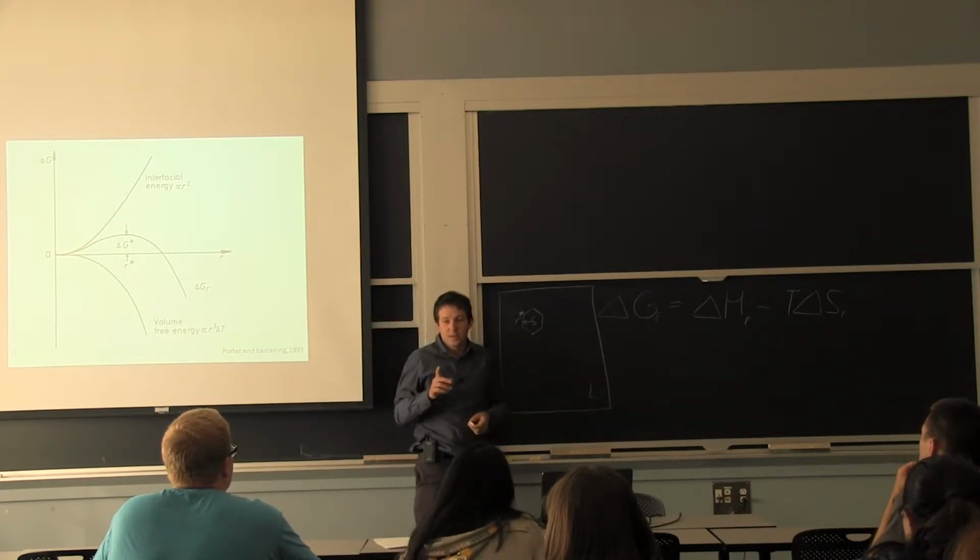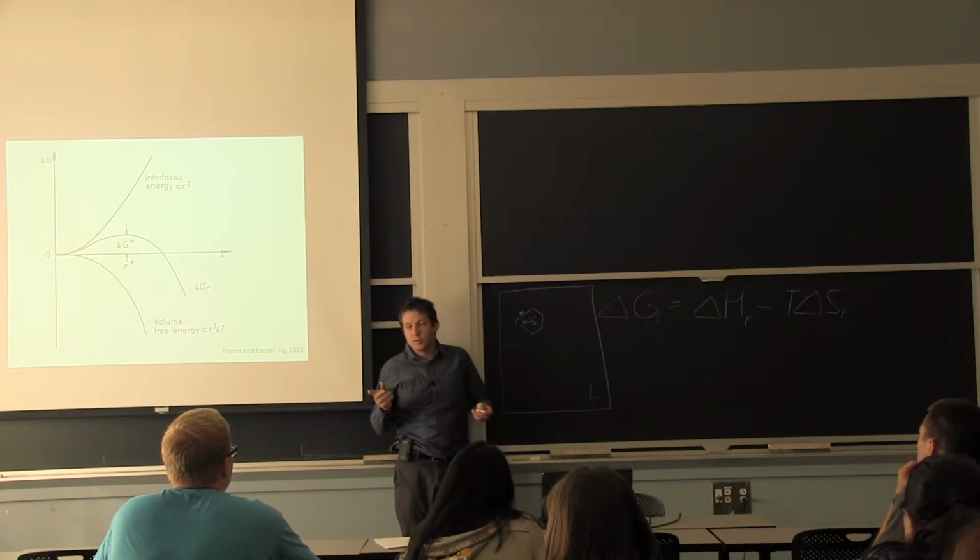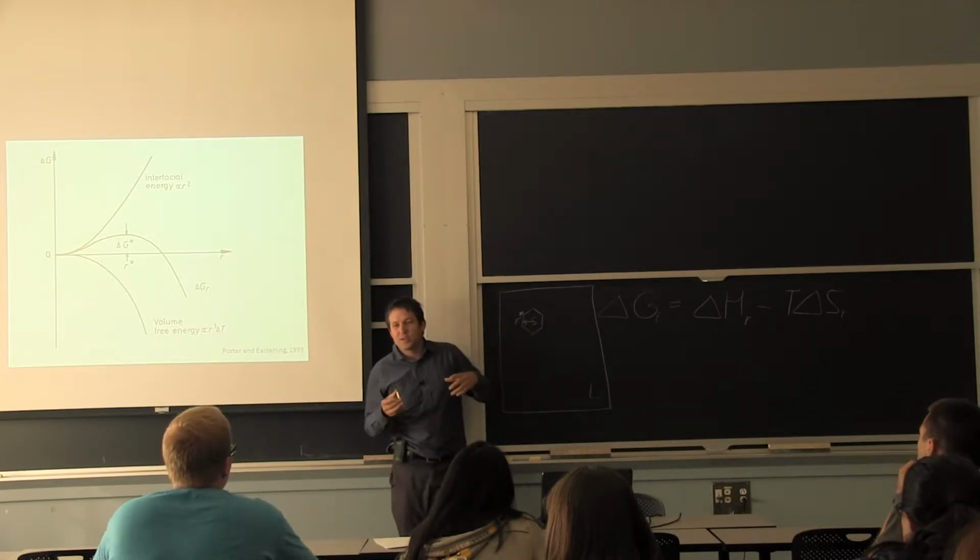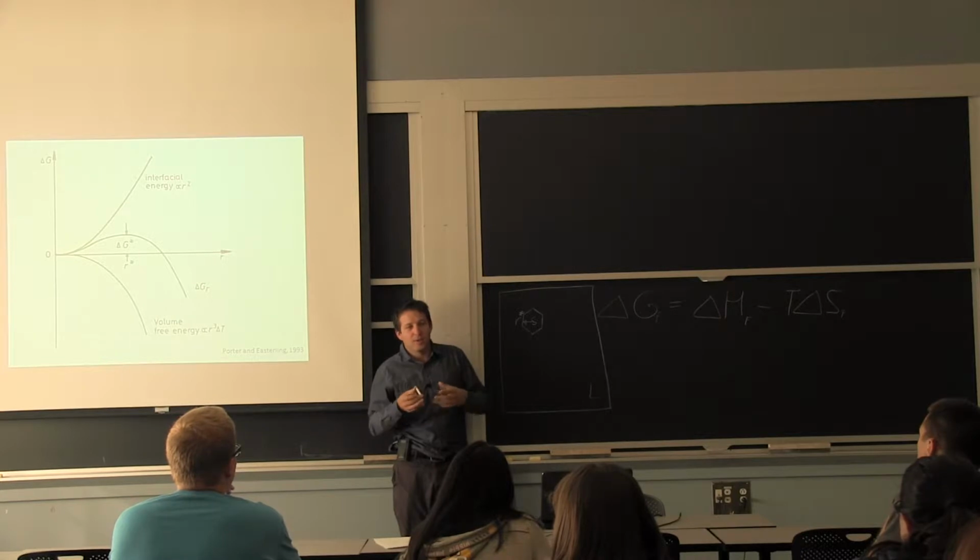I would say though that if you deform some of these amorphous metals, or we call them bulk metallic glasses, they will form some crystals, because the deformation essentially activates the movement of the atoms and helps them get back to where they want to be in terms of equilibrium.